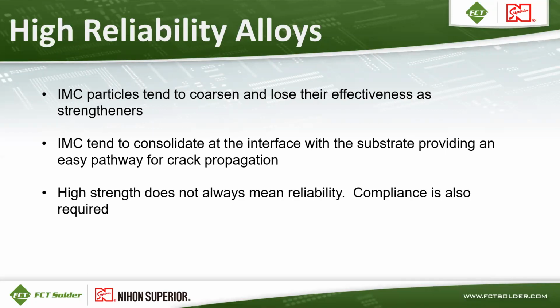High strength in solder does not always mean high reliability. What I mean by that is if the solder joint is too strong, then that can cause pad cratering type defects. During thermal cycling, the materials within the circuit board, the solder joint, and the component are all different, and they have different coefficients of thermal expansion. As those materials expand and shrink with heating and cooling, they do that at different rates. If the solder joint is not compliant or doesn't move very well, then it can potentially rip the pad off of the circuit board. So that can cause reliability issues.